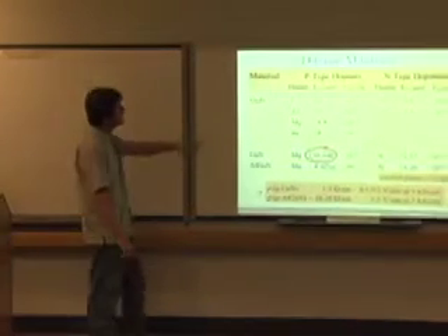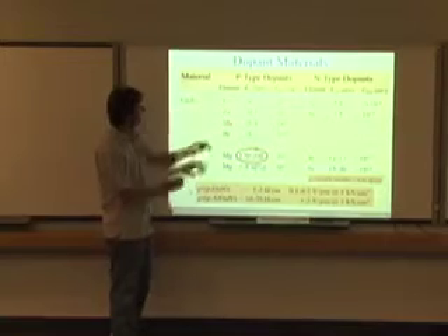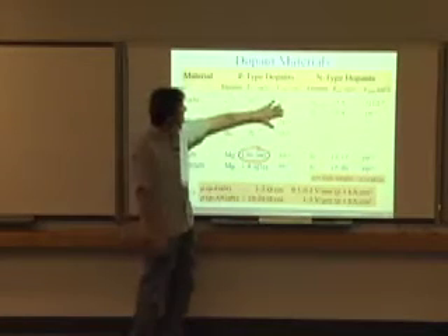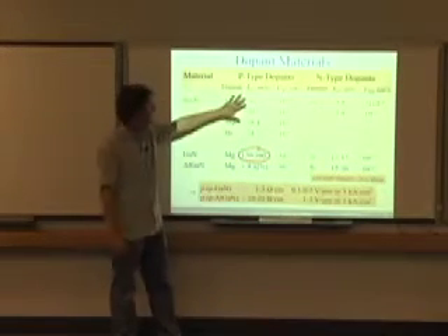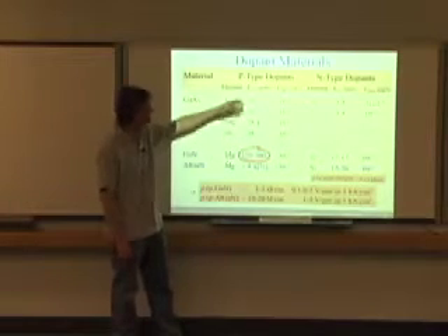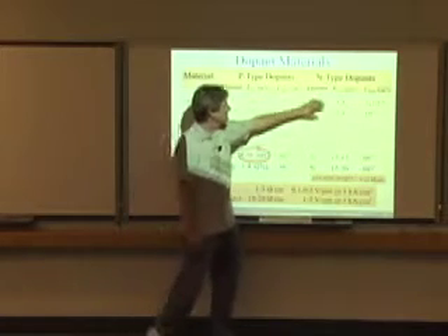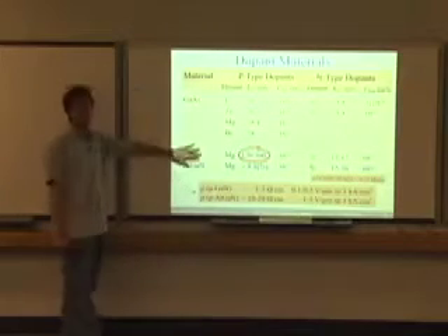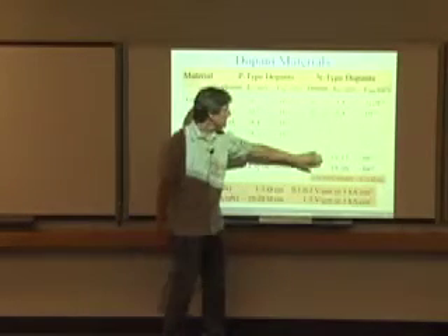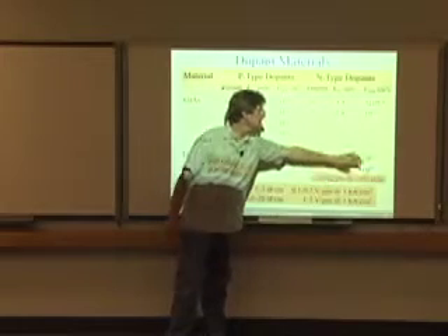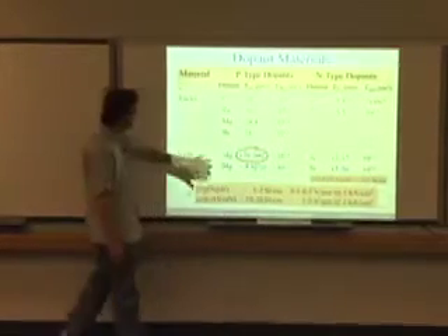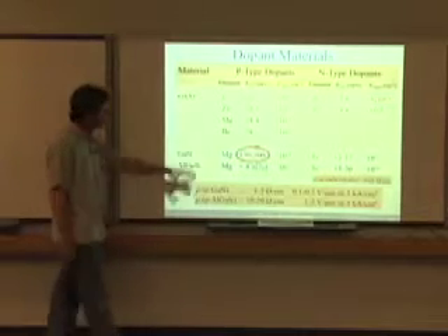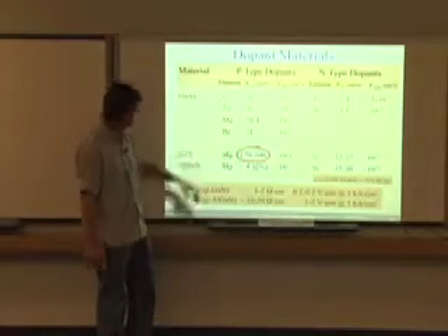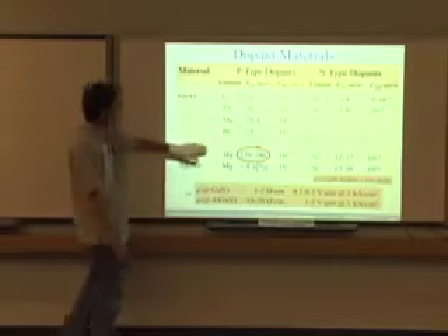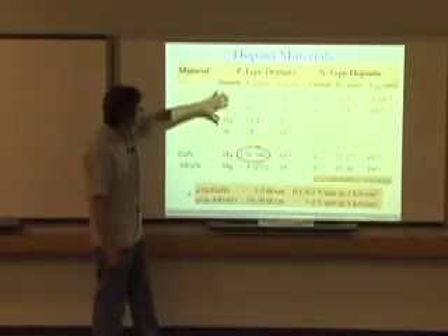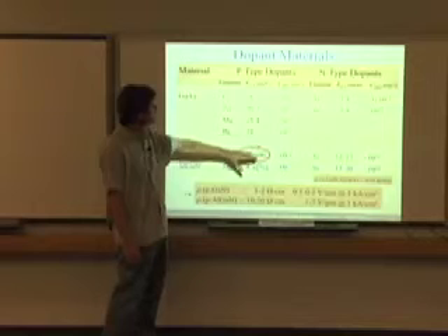If you look at dopant material choices for gallium arsenide, you've got a whole host of dopants that you can choose from. High max concentrations can be achieved at low activation energies, very easy to ionize. N-type, you had a couple of choices there, also very good. If you look at gallium nitride, the N-type is also very good. You can get very nice activation energies, max concentrations are very high, so N-type doping in gallium nitride is not a problem. The real big issue is P-type doping in gallium nitride and InGaN, which Shuji can tell you all about. Magnesium was the dopant of choice, and it has very large activation energy.